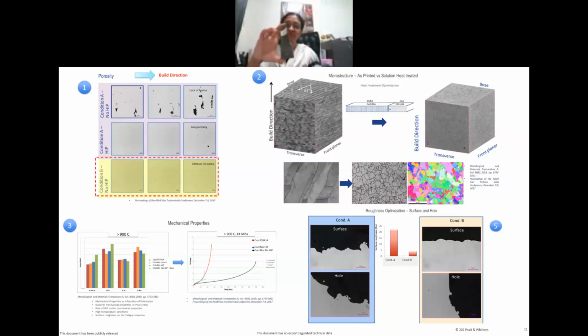So how do I make sure the heat transfer is actually reproduced via additive manufacturing as I build this part layer by layer, in order to ensure that the parameters I choose in a bulk part, which give me a dense energy density resulting in a dense microstructure, still work? How are we able to resolve between different energy densities or laser parameters, all of which give you a dense part? So I'm really trying to show you, 4 or 5 years later, the challenge that we face right now, which is why we always partner with integrated computational materials engineering to predict and to validate together. So that is challenge number one.